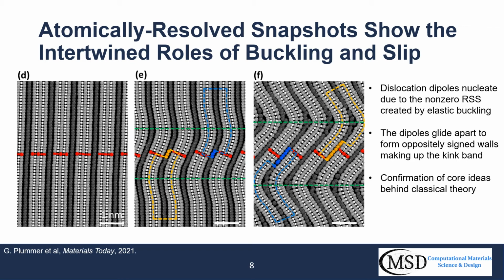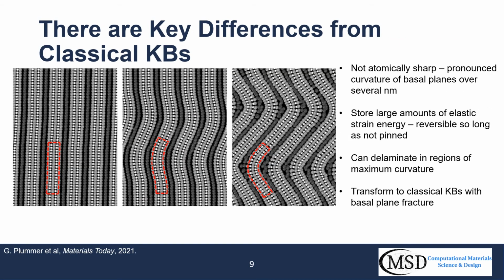There are, however, some important differences to note. The kink boundaries we see here are not atomically sharp, as has been typically assumed, but exhibit a pronounced curvature of the basal planes over several nanometers. The layers have only deformed elastically, as indicated by the closure of Burgers circuits drawn even at extreme kinking angles. As such, we expect these boundaries store large amounts of elastic strain energy, making them reversible so long as they don't become pinned by lattice resistance to dislocation glide.